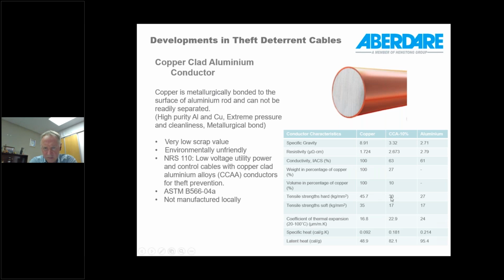Tensile strength is quite a bit lower than copper. Coefficient of expansion is also significantly different, and of course this is where some of the problems come in between, let's say, aluminium and copper: the rate of expansion is different, and you get loosening of connections when you're using small sizes of aluminium. But this has really been addressed by copper-clad aluminium and the use of 8000 series alloys within these types of conductors.